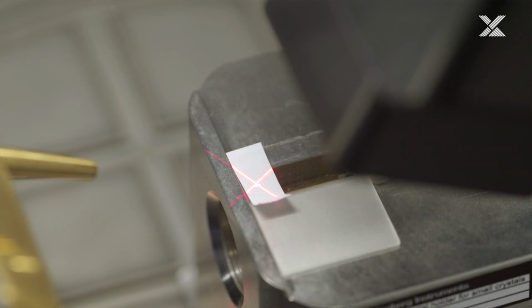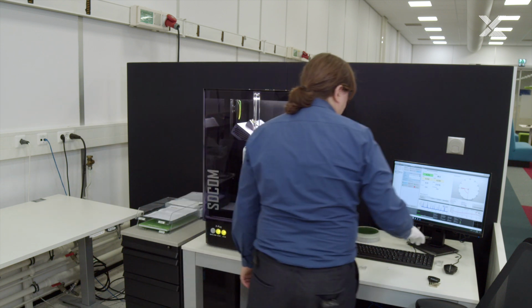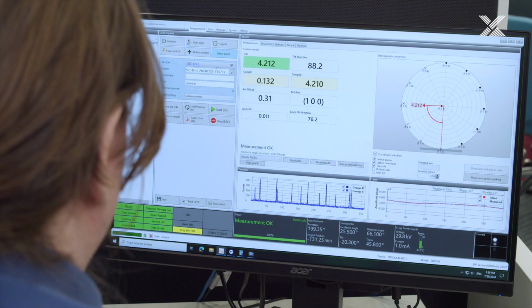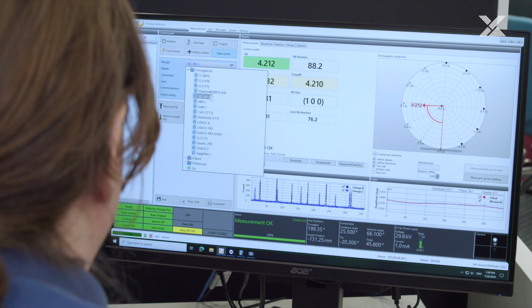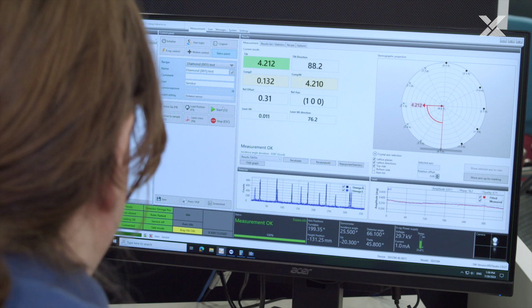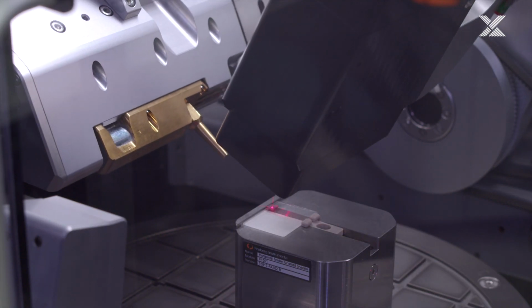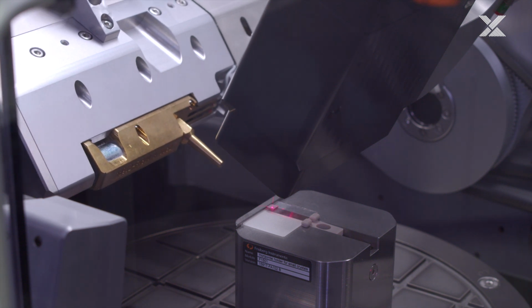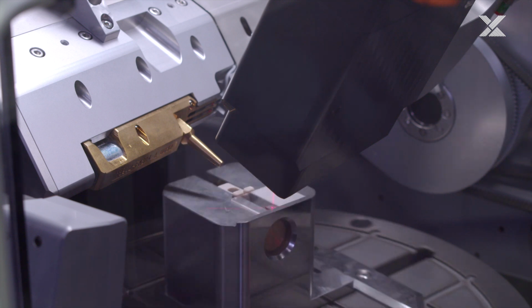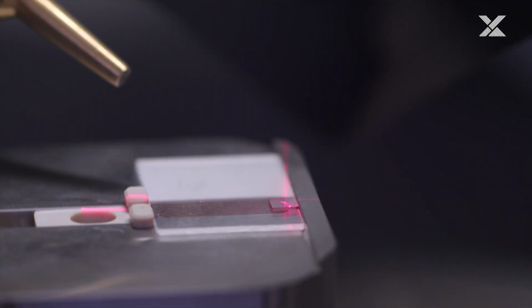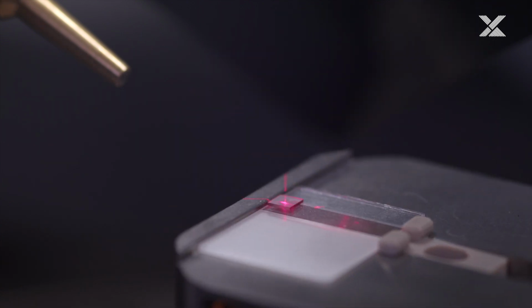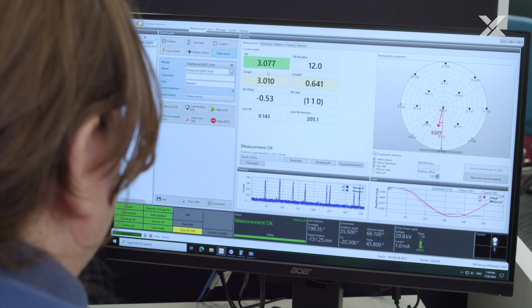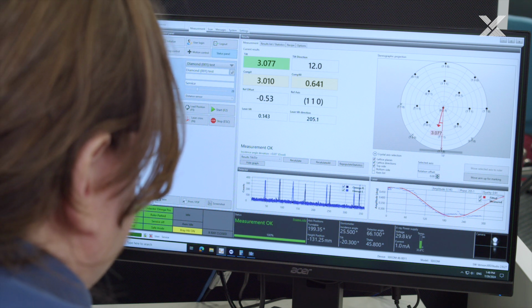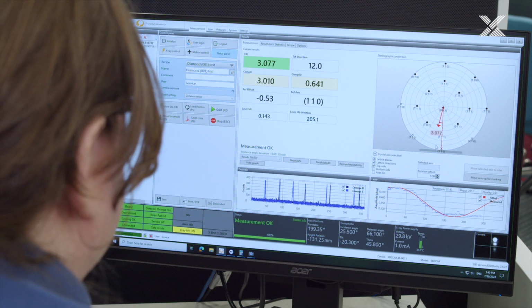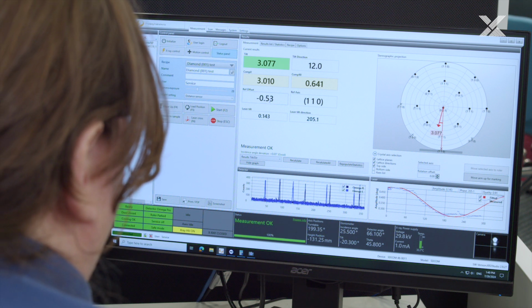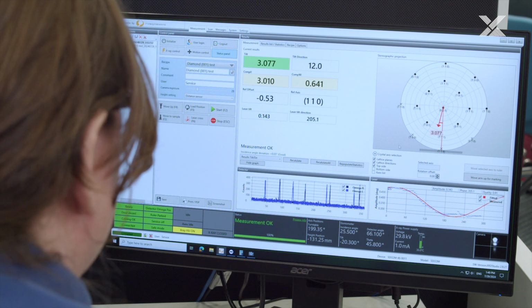All right. Close the system. We've done our height alignment. Now we need to select our Diamond 001 recipe. Again, take over that name, and then we can measure. So, in this case, we've got about 3 degrees of tilt almost directly in the -1, -1 direction, which is the reference direction in this case. And there's only a very small angle of 0.53 degrees between the bar and that flat in this case.